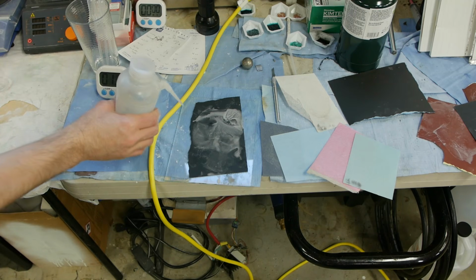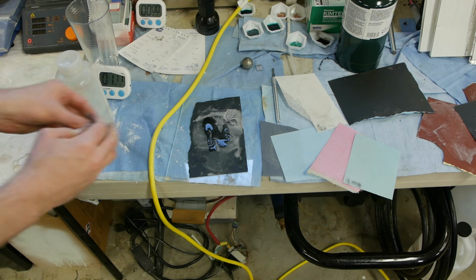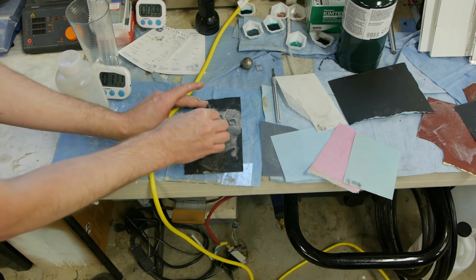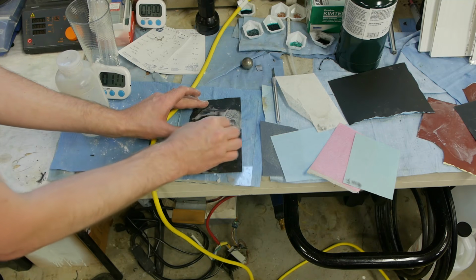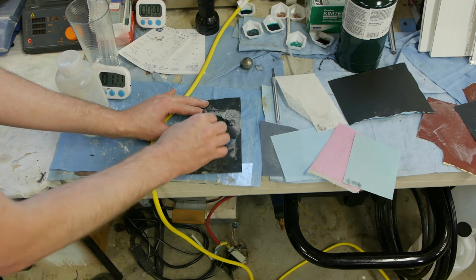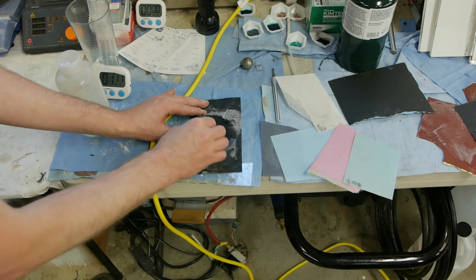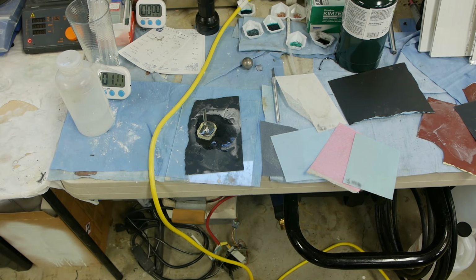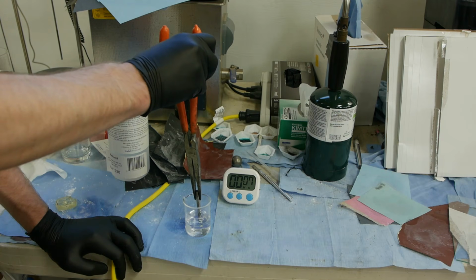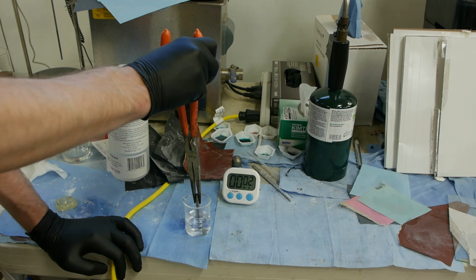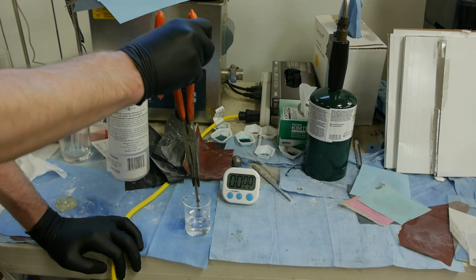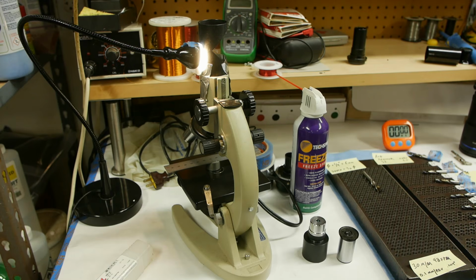One, you have to polish the surface of the metal to an absolutely great degree, right? Because the structures that we're looking at are only tens or hundreds of microns big. So if the surface is scratched, even with tens of microns level of scratches, you won't really see any of the structure. So that's one step. Then you have to etch the metal with a special etchant so that only the certain regions you want to see are etched, right? You need contrast. If the etching applied equally to the whole surface, it would just move down and you wouldn't see anything. So we need an etchant that preferentially attacks certain structures over others.